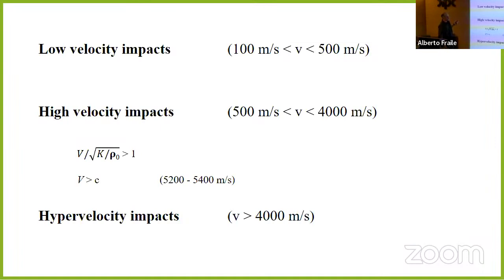And then what we call hypervelocity impacts, because the title can be why hyper. We can talk about low velocity impacts when we are below 500 meters per second, more or less. Then we talk of high velocity impacts above 500 meters per second and below 4,000, more or less. And this number, 4,000, can be calculated like the square root of the compressibility divided by the density, or can be just taken as the velocity of sound in the material. So more or less 4 kilometers, 5 kilometers is the limit or the threshold between high velocity and hypervelocity.